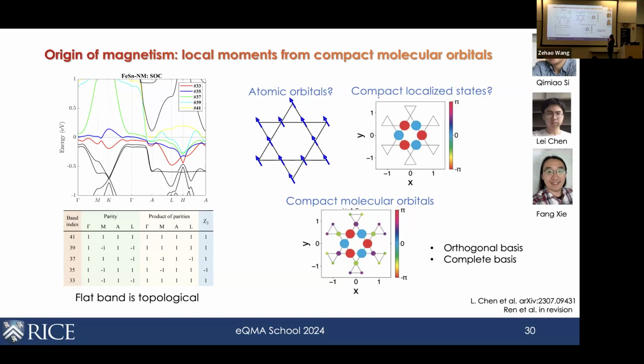Which means you can't really write atomically localized states for these, like the local moments that we are used to dealing with. So here they have constructed what they call the compact molecular orbitals. In this way, they can actually generate an orthogonal basis that's also complete. And with this description, we can think about the object that's carrying the local moment as perhaps coming from these compact molecular orbitals, which are not atomically localized states, but extended like this.